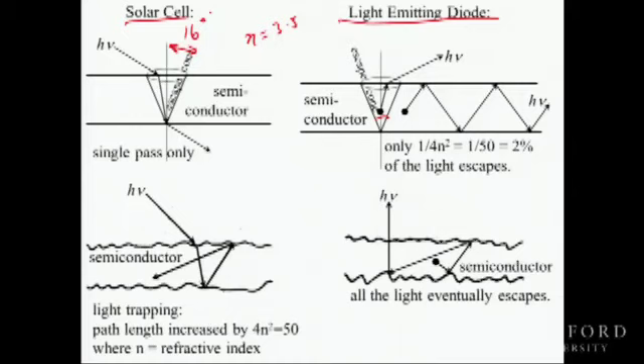Let me show you the same problem in a light-emitting diode. The light-emitting diode is the inverse of the solar cell. In a light-emitting diode, you're trying to get the light to escape, but only the light in the escape cone. If it's only 16 degrees, what percentage of all the outgoing light is that? That's only about 2% of the light, and that's where that 4n squared factor comes in. If you're going larger than 16 degrees, you get totally internally reflected, again and again, and you get trapped. Believe it or not, they used to make light-emitting diodes this way. They didn't take this into account.